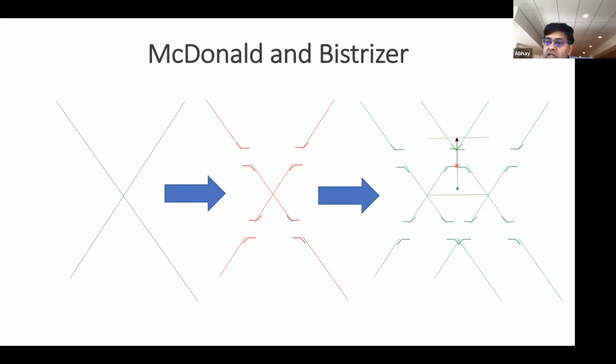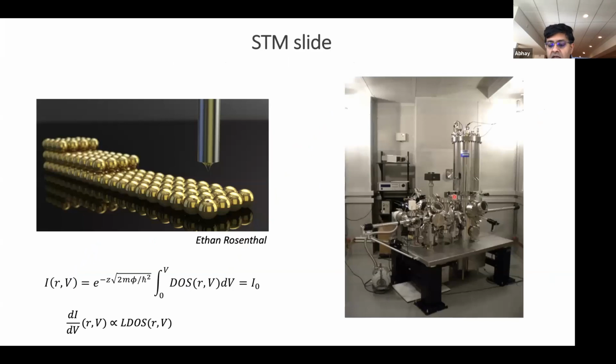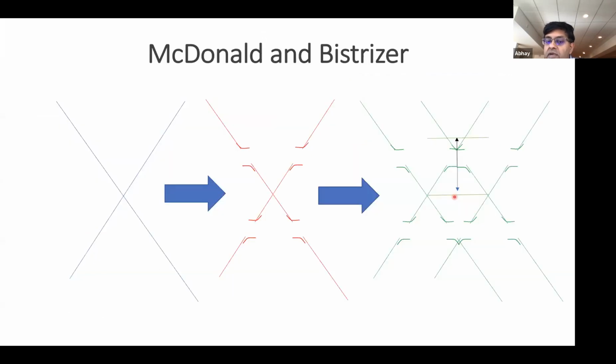And if you tune the angle exactly right, then one of these states, they showed, has this amazing property that it's perfectly flat in momentum space. So within this simple calculation, it was a band that has absolutely no dispersion, so it's perfectly flat. And this was the motivation for many people to do their experiments to see if one can actually find this flat band structure.